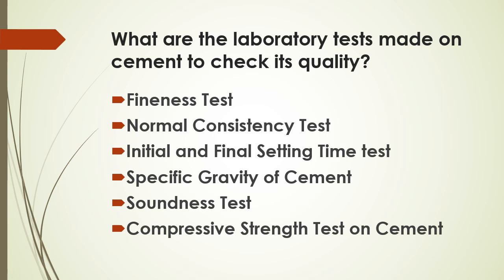The compressive strength test uses small cubes of size 70.6 mm × 70.6 mm × 70.6 mm. These cement cubes are cured for 7 days, 14 days, and 28 days, then tested under a compressive strength testing machine. The 28-day value is taken as the compressive strength of the cement, which defines the grade of cement.